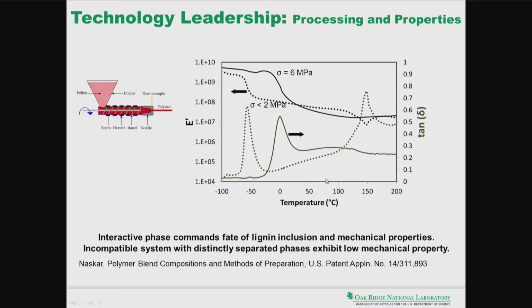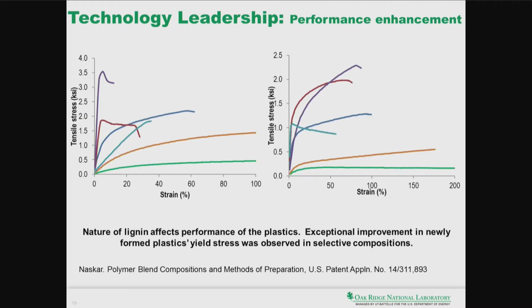And we exploited that, and in fact, we filed a patent application on this particular concept. Then our focus remained, now can we further improve the mechanical properties beyond 6 megapascal? So we did several formulations, and the tensile stress strain plots are shown here on the left part. You would see, so this is the red curve. That was the material almost like 6 megapascal tensile strength we were talking about. Now, unfortunately, here I'm showing the tensile stress in KSI, industrial unit, not in SI unit. So 1 is equivalent to nearly 7 megapascal.